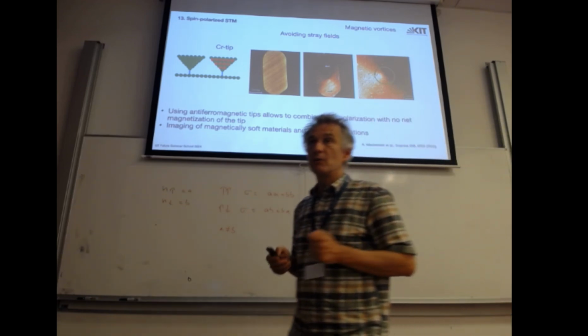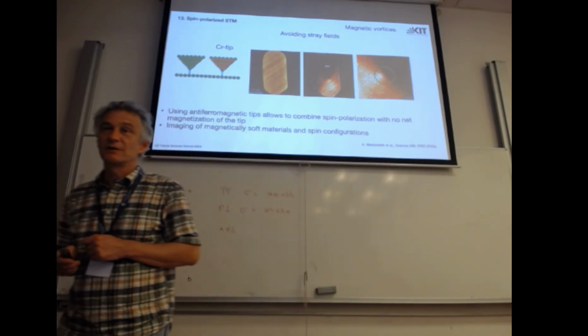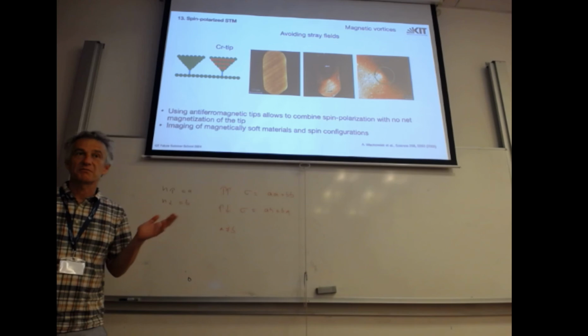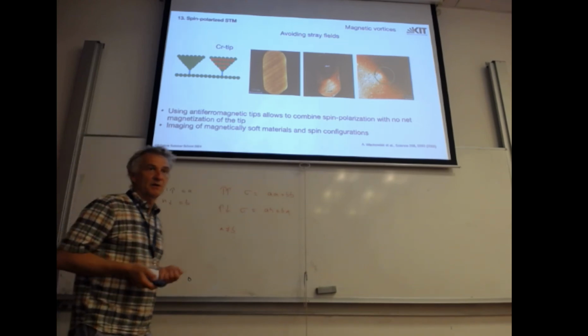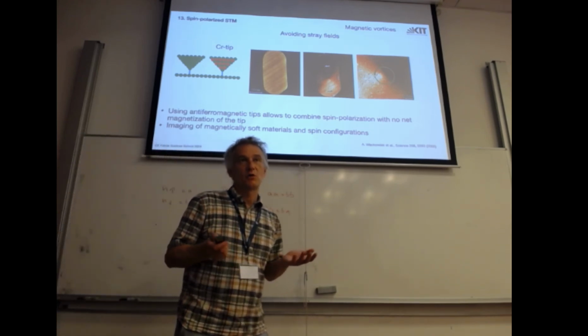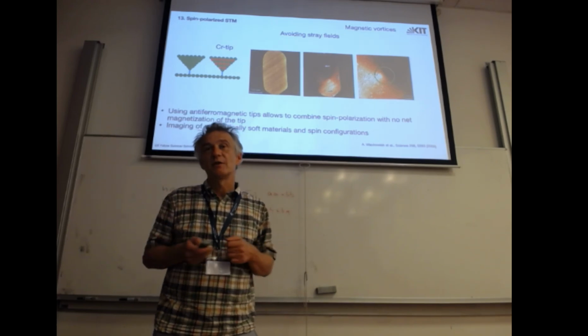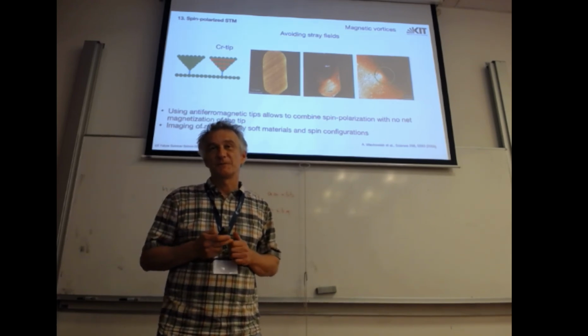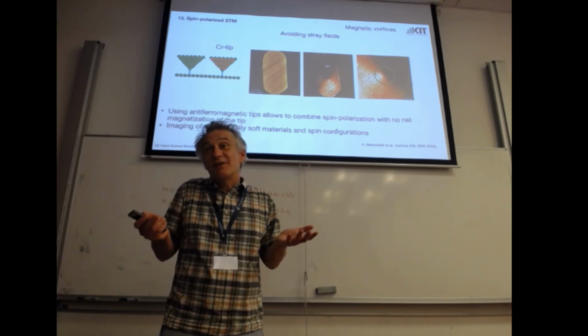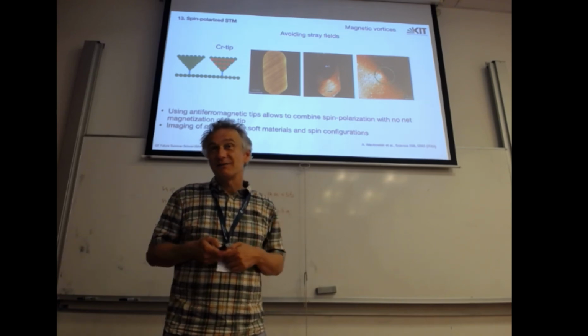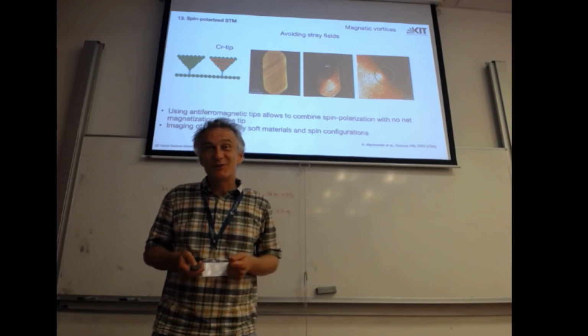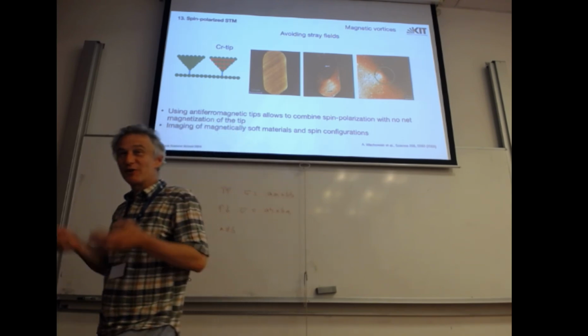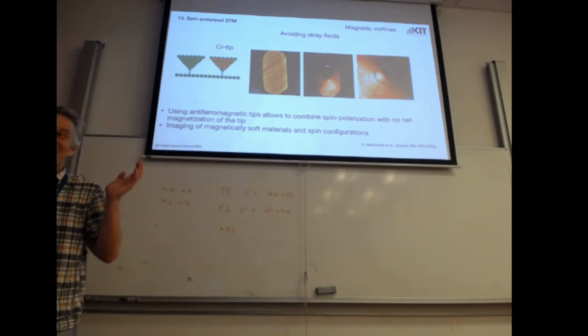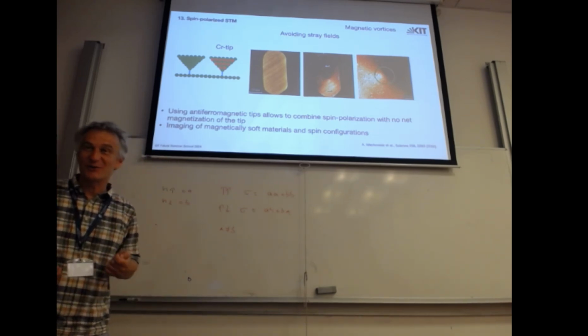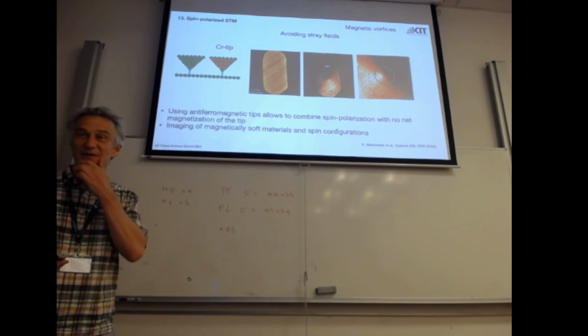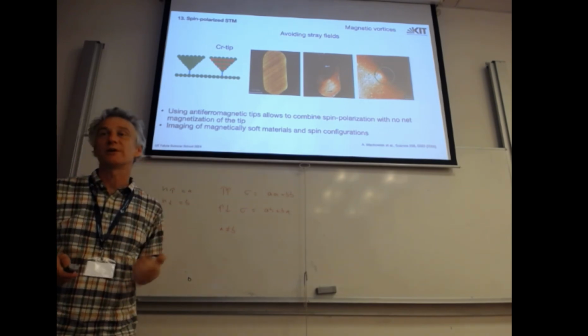It's usually what is called the Gilbert damping, and the damping is, let's say, for typically good materials, a couple of percent of the energy. That means if you have an energy of a milli-electron volt, then the time is like 0.01 milli-electron volt. So this is, I don't know, somewhere in the picosecond range. So they don't live long.